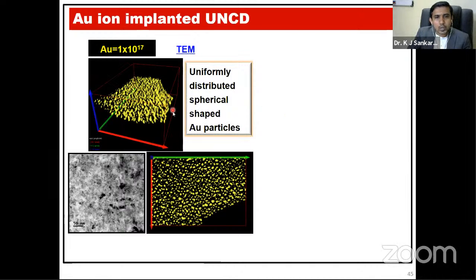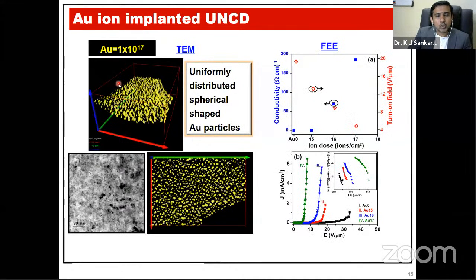And how are the gold ions present in the UNCD? This is the TEM image, a HAADF image that we acquired of the gold ion implanted UNCD. These gold nanoparticles are present in a spherical shape in the UNCD films. With the presence of the gold nanoparticles inside these UNCD films, the conductivity of the material is improved, and by increasing the gold ion dosage, the turn-on field is greatly decreased, and the current density is really increased.